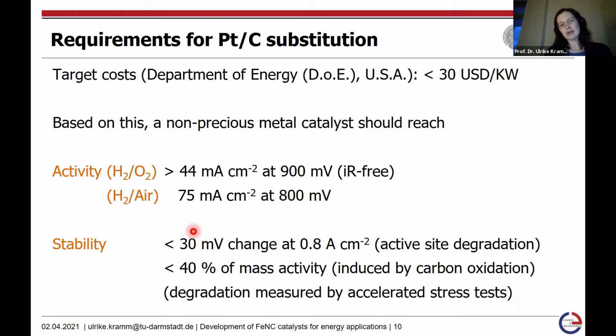With respect to the stability, the aim is that with respect to active site degradation, they should lose less than 30 millivolts in order to obtain a current density of 0.8 amps per square centimeter. And the mass activity loss, which is induced by carbon oxidation, should be less than 40%. These degradation tests are related to accelerated stress tests. I will later show you one example of such protocols, how they can look like. You continuously cycle in a distinct potential window, and the potential window to measure the active site degradation is different from the potential window for the carbon oxidation study.